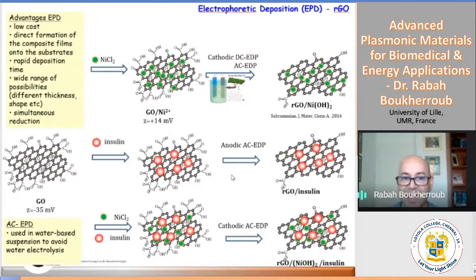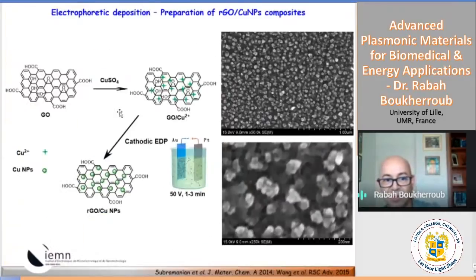Interesting enough is that if I mix this graphene oxide with nickel, or with a biomolecule, or with any metal ion, I can actually make hybrid materials very easily in one step in less than a minute. One example is I took graphene oxide with copper salt. You just apply a voltage of about 50 volts for 1 to 3 minutes. I can actually control the thickness, and you end up with copper nanoparticles.